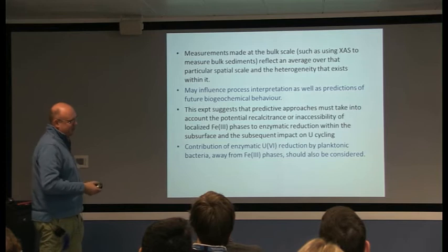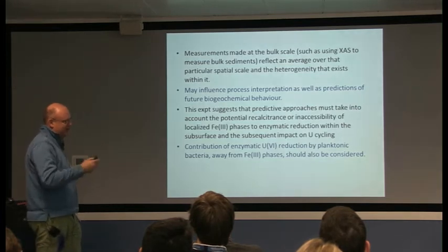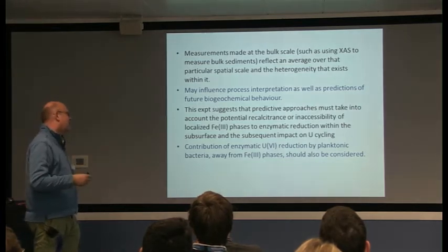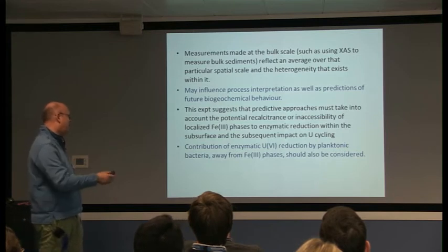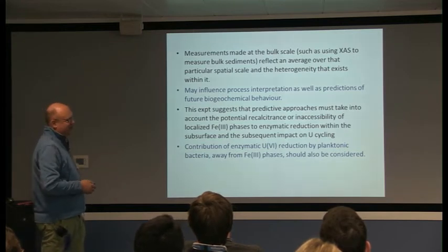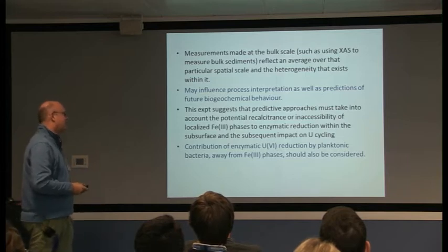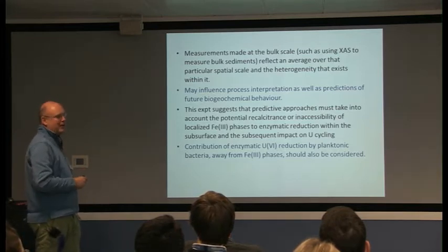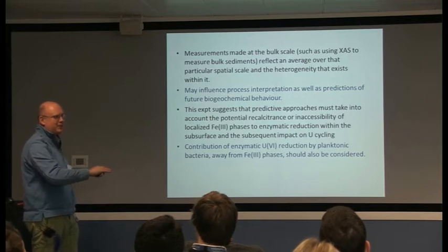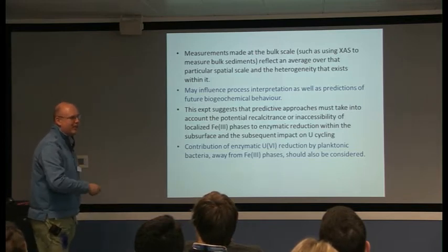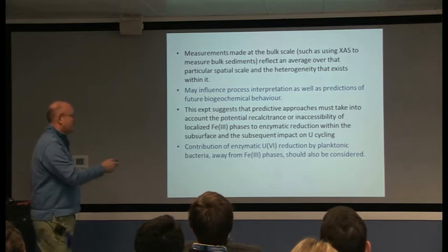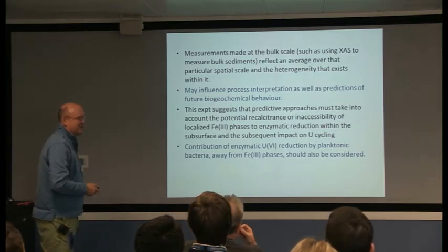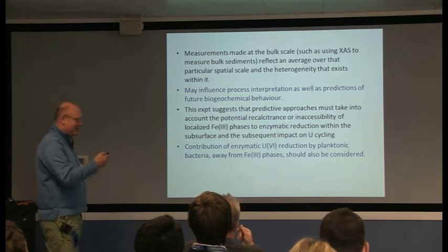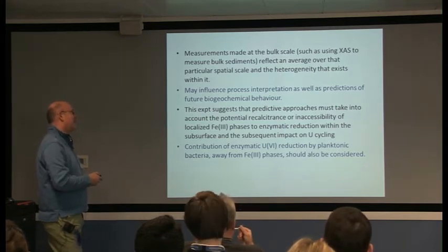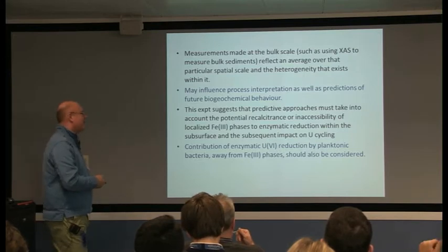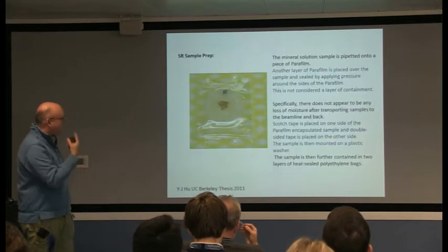If you do that at the bulk scale, you don't necessarily see the difference, so you really need to consider how bacteria can reduce uranium-6 when there's no iron around, and also whether flow means that your modelling, if you just consider results from bulk reactions, may not give perfect results, because things hide in different places and not everything's going to mix necessarily in a pore flow through a microfluidic environment.